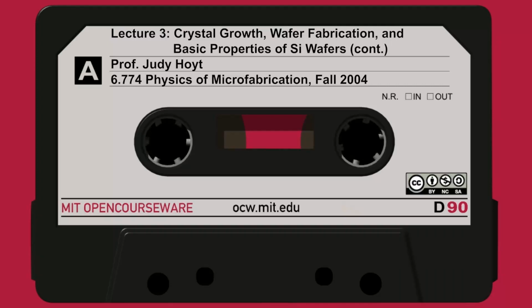So before, when I had it at mid-gap, the dominant charge state was neutral. As I move it up, all of a sudden now I've got lots of V minus. If I move it up even further above this V minus, V double minus, I'll have lots of those. So as I move the Fermi level up and down, just imagine with doping, I can control the concentrations of these types of vacancies, these charged vacancies, either V minus or V plus.